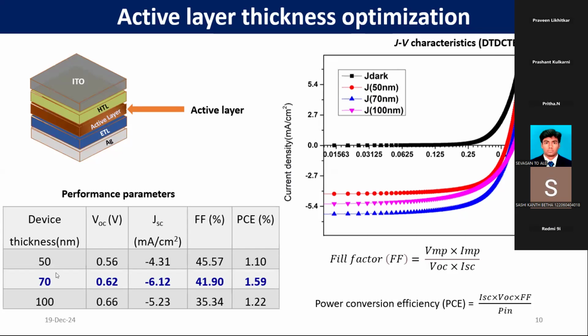So different thicknesses of the active layer, and then I have verified their performance parameters like open circuit voltage, short circuit current density, fill factor, and efficiency. So at 70 nanometer, it is able to give 1.59 percent power conversion efficiency.